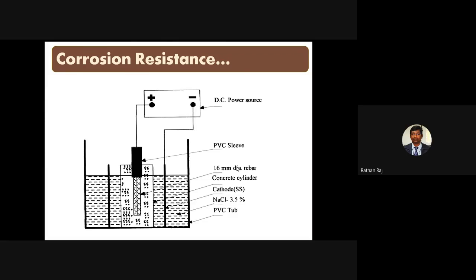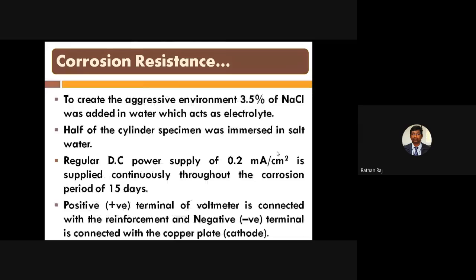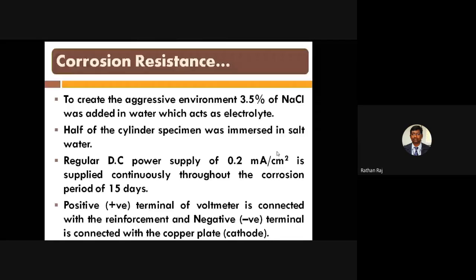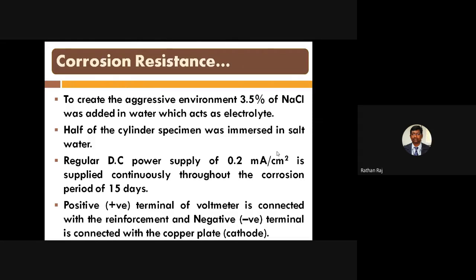To create the aggressive environment, we have to use sodium chloride solution. Here 3.5% sodium chloride was used, which acts as an electrolyte. Half of the cylinder or 3/4 of the cylinder was immersed in this salt water. A regular DC power supply of 0.2 milliamps per centimeter squared is supplied continuously throughout the corrosion period of 15 days. The positive terminal of the voltmeter is connected with the reinforcement, and the negative terminal is connected with the copper plate, which is acting as a cathode.